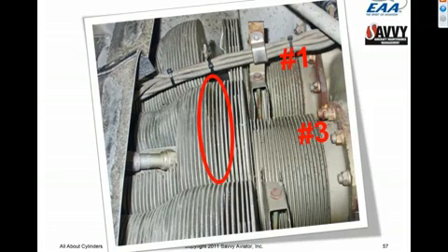To have 2 catastrophic head to barrel separations like this within 30 minutes of one another is quite extraordinary. Somebody up there wasn't liking this owner. It was a Florida-based airplane. You can see there's a lot of corrosion everywhere. The corrosion probably had something to do with setting up stress risers on these cylinders. It also happened to be the high compression version of the Skylane engine, the O-470-U, with a higher compression ratio, and we see head-to-barrel separations more frequently on that engine than on the lower compression versions of the O-470. Here's another head-to-barrel separation.